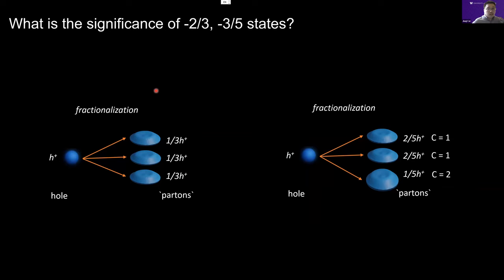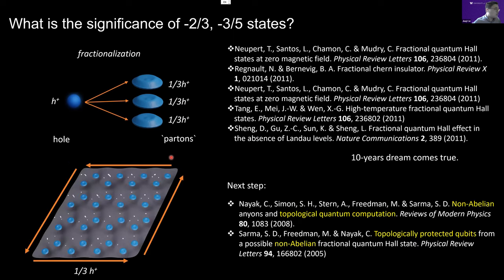Okay, so after establishing topology, magnetism, and also correlated states inside the system, what's the significance of this observation? As I previously introduced, the strong interaction can fractionalize this quasi-hole into parts of it. And what we observe is that two states, nu equals minus two thirds and nu equals minus three fifths, are actually those kinds of fractionalized states that are supposed to host the fractional version of holes. So what people can expect is those holes will form dispersionless edge states and give rise to the quantized fractional Hall signal in transport measurement.